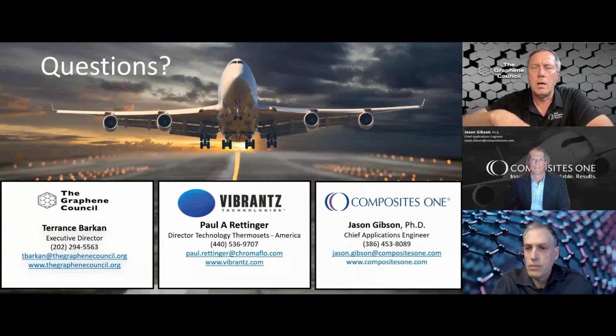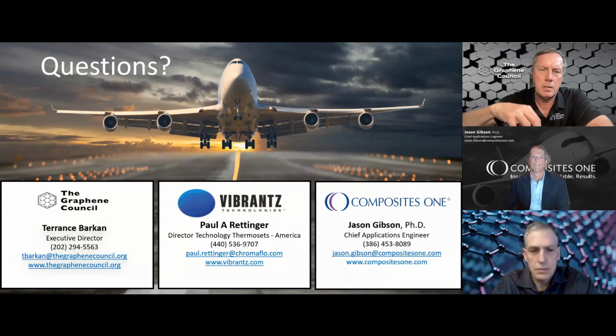There was a question if the graphene was provided in liquid form or powder. This was all powder, right? Ideally, if you're a consumer of this material or a composites maker, you don't actually want to handle the graphene yourself. What is proposed here is the ideal solution of having the graphene already master batched into a resin system that you can just use, and as Jason just said, without having to worry about the compounding part of it yourself, and just go ahead and use it and get the benefit of the properties without having to handle graphene as a nano powder. And when we talk to anybody, and for all applications, we recommend this approach of working with master batches, work with a graphene producer or a specialty company who can do the compounding, so that you're not having to deal with the nano powder if you can avoid it.